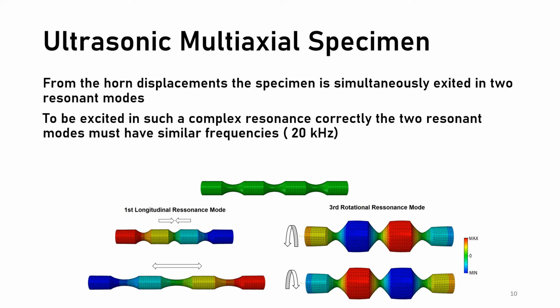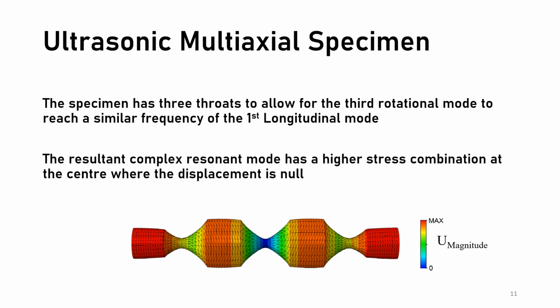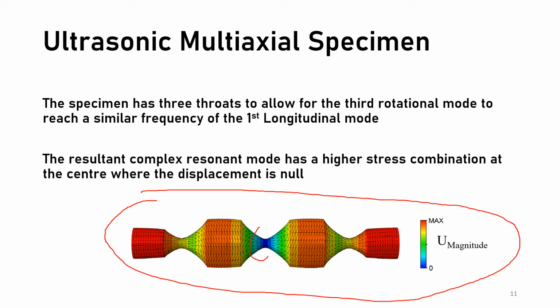For the axial displacement, the specimen is excited in the first longitudinal resonance mode, where it compresses and stretches, having only one region of high deformation, very similar to the tension compression in the actual ultrasonic fatigue specimen. Now, for rotation, the specimen needs to have 3 throats in order to have a 20 kHz third rotational resonance mode. This creates 3 different high shear deformation regions, where the specimen in the cylindrical regions changes direction between throats. When it's excited in the two presented modes, the first longitudinal and the third rotational, the deformation result is presented on the bottom, with one single high deformation region, the fatigue testing region.